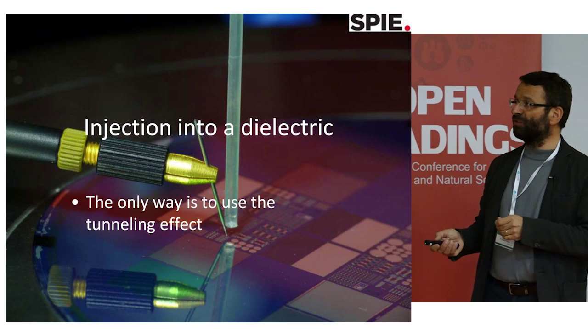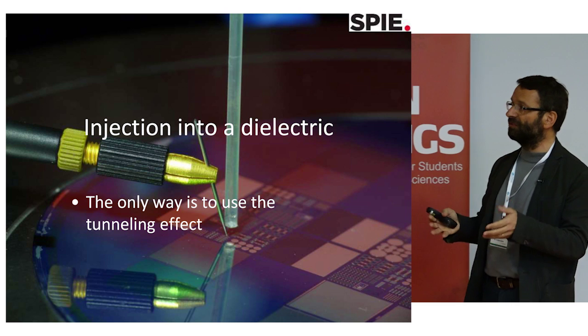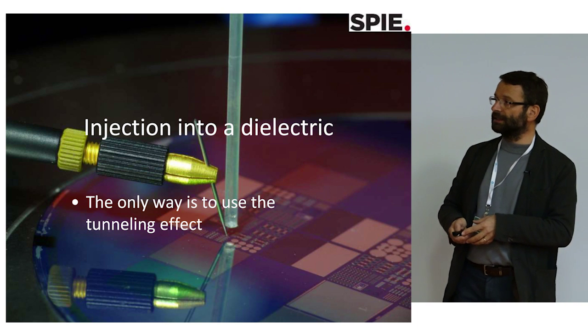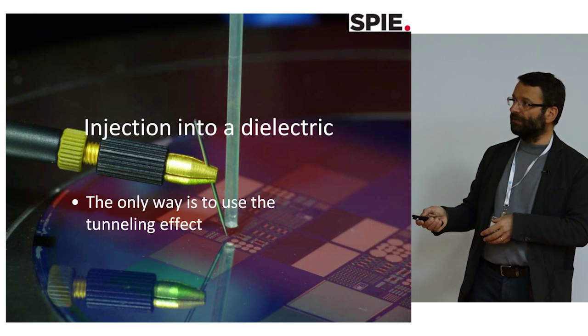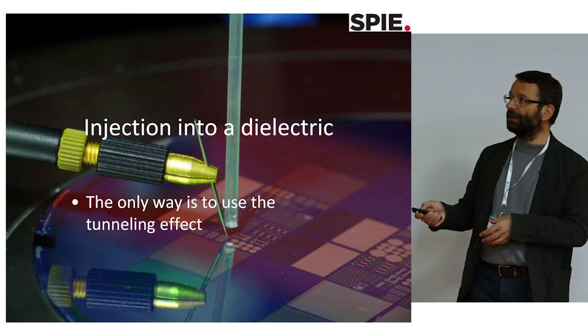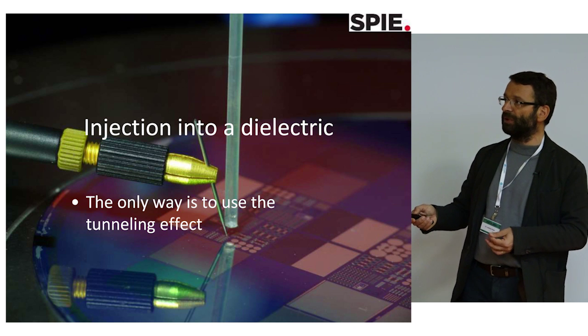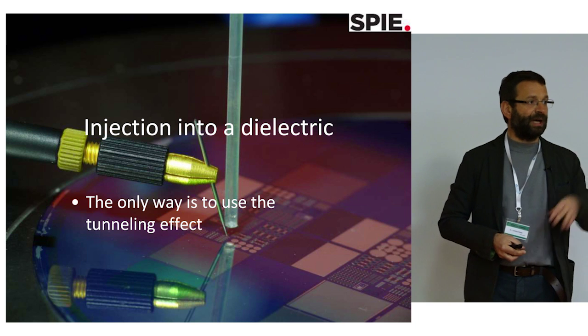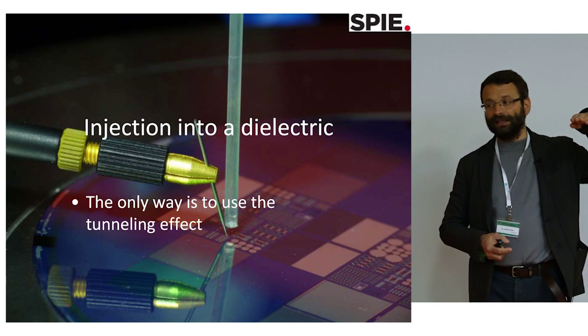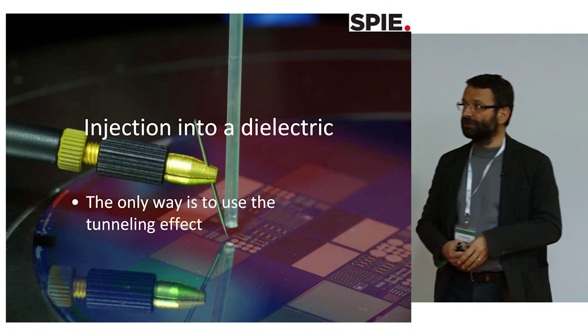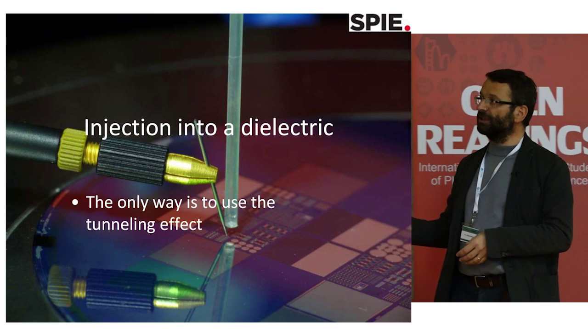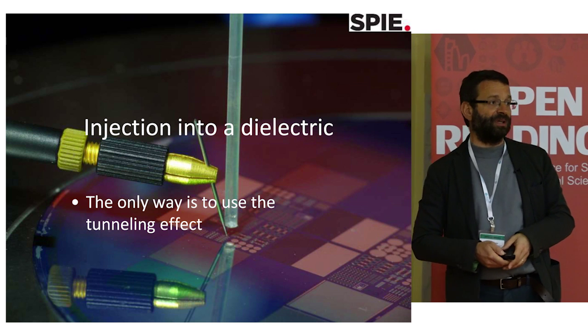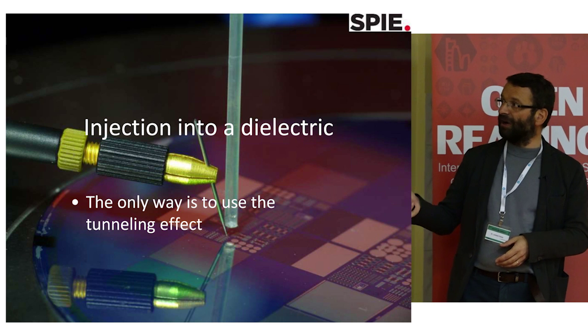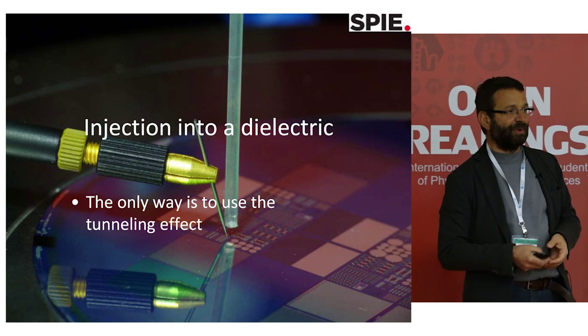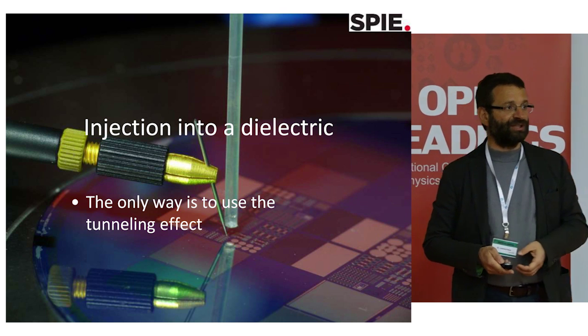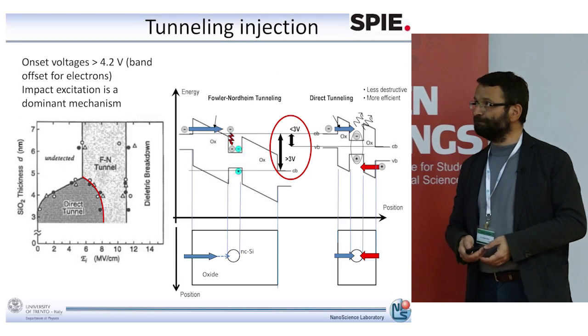Here is an example of a wafer where we have made a few of those silicon nanocrystal LEDs, in various geometries, and then the experiment is very simple. We use a needle just to contact the top surface of the LED, and then the back contact is on the bottom of the wafer, and then we collect the light by using an optical fiber. This is a plastic fiber, so it's a very simple experiment. And then we look at how much light we can get.